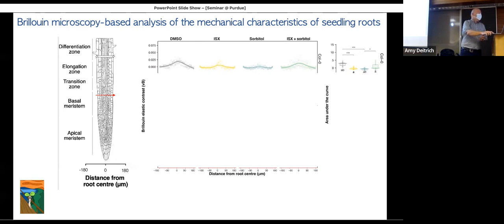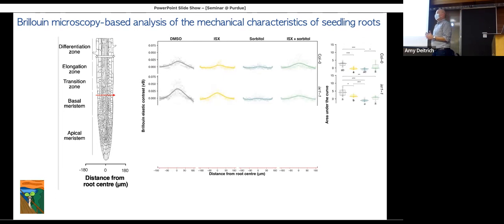If you do the same experiment with the isoxaben-resistant mutant, what you observe is that the stiffness in the mock-treated situation is elevated compared to wild type. And I think this is again part of a compensatory reaction when you reduce the cellulose, so other cellular components are being integrated. You see a bit of a decrease with the isoxaben, but you see the same response to the sorbitol as with the wild type, suggesting that the IXR mutation is not affecting this response, which you would expect, because it's not a signaling mutant but a biosynthetic mutant. And you still get a bit of an elevated stiffness again in the double treatment.